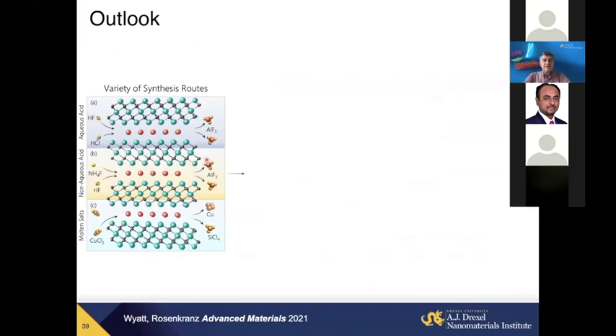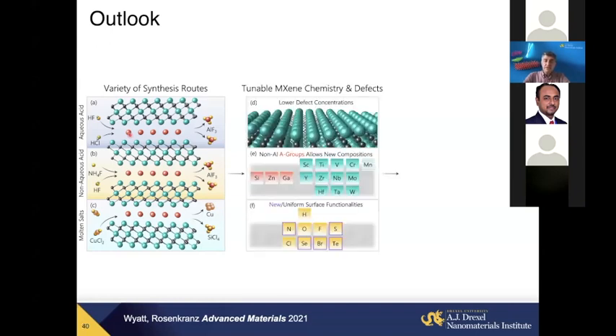Just because, as we talked today, there are a variety of MXenes. Just varying the method of synthesis allows us to produce different surface terminations, different chemistries, even for the same MXene. Ti3C2 we discussed today is actually a very good MXene because titanium and carbon are both very abundant elements here. But you can say the same about Ti2C or Ti3CN, carbonitride, or titanium nitride. And there is a good probability that some other MXene with, say, molybdenum or vanadium may appear to be even better lubricants.